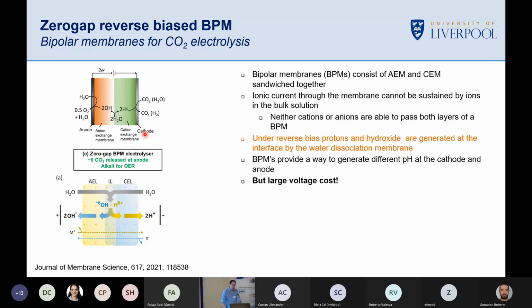So if we now contact our cathode directly onto the cation exchange layer, so we're going to use what we call a zero gap operation structure, which is beneficial and can potentially give quite high current densities. We're going to have a very low local pH for our cathodes. It's going to be nice and acidic, which is what we want.